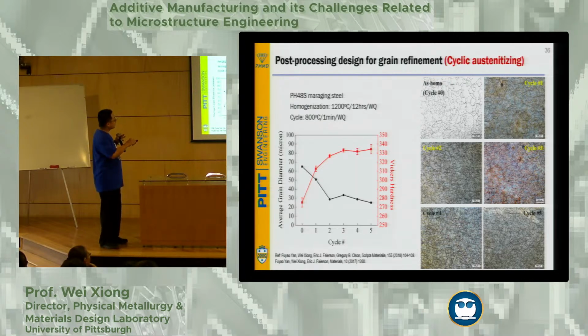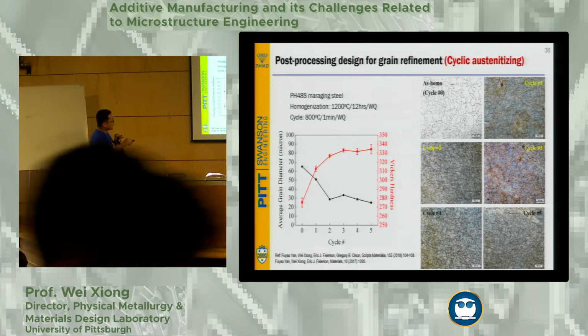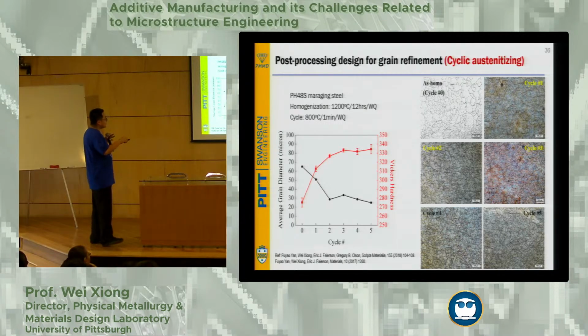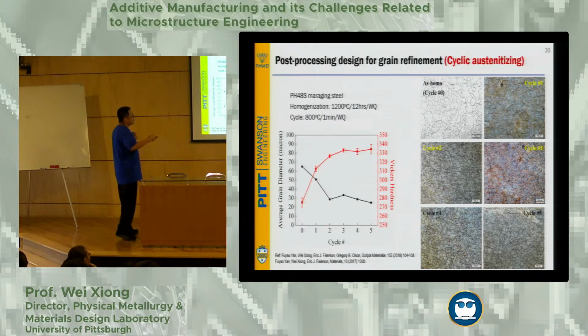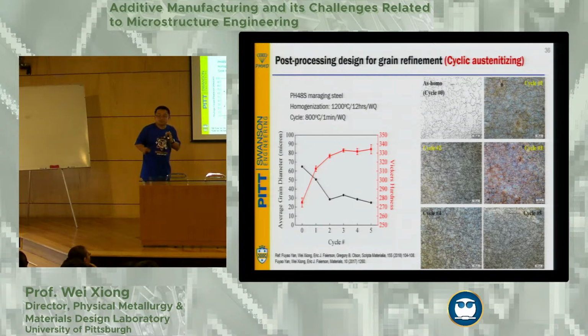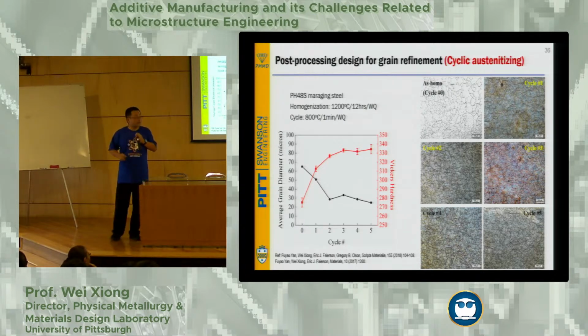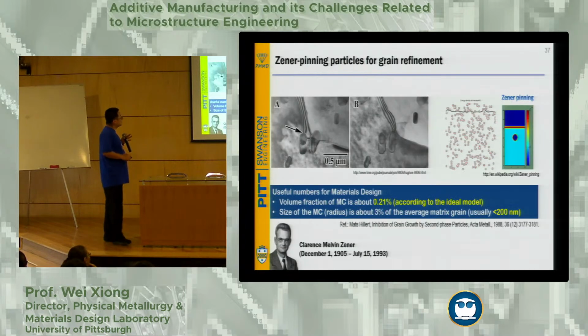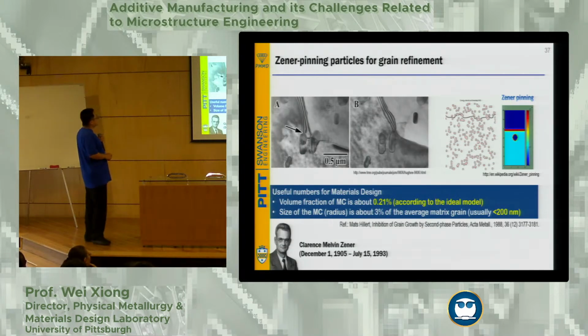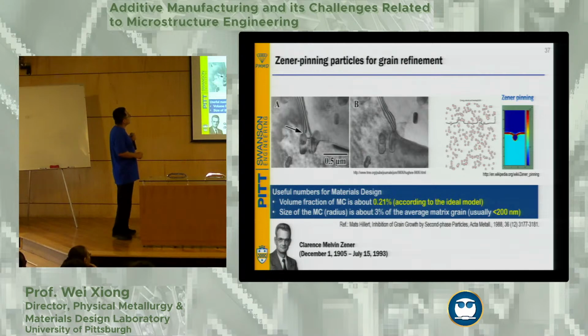And of course the hardness is also reaching almost the same at these cycles. That means within 3 cycles you can actually refine the grains. It's a very encouraging story, showing that traditional metallurgical concepts still apply.